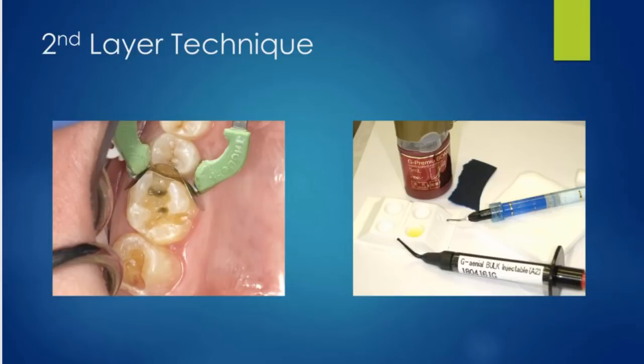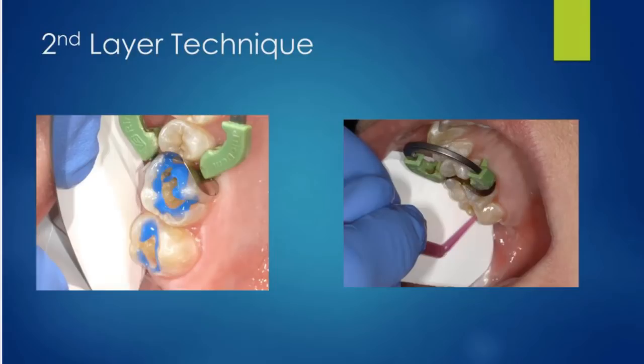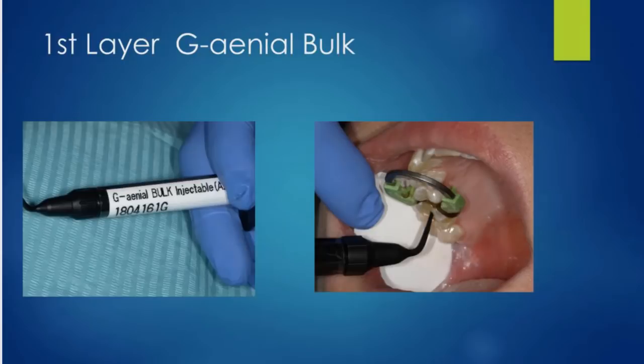So this is the tooth in question that you see here. This is tooth number 14. And you can see where this was a large MOL composite. 15 had a large occlusal behind it. 15 was not so deep, so that was able to be treated in 1 bulk fill. But when we look at this, there's our selective etch, application of our G Premio bond. You can see I only got a couple of colors when we started placing this, so I was having to be pretty selective with the cases that I chose.